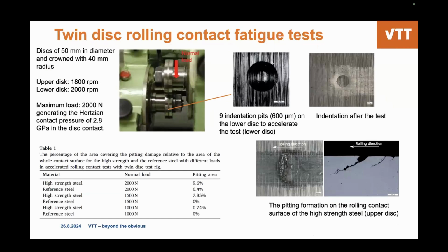Here is more detail about the rolling contact fatigue test. We have this twin disc with 50 millimeter diameter, and the surface is crowned. The upper disc runs at 1,800 RPM, the lower one is slightly faster at 2,000 RPM, and the maximum load was applied here. So we have applied different normal load levels, as you can see in this table, for both the newly developed high-strength steel and the reference steel.